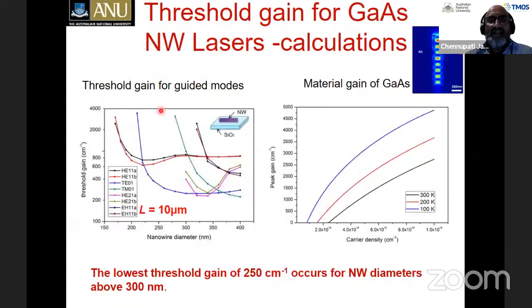So in fact, he has done calculations of the threshold gain needed for making these lasers work, as a function of the diameter of the nanowire. And you can see that the smaller the diameter of the nanowire, the threshold power, the gain needed to really make these lasers work, is very, very high. That means before you even start being able to make these lasers work, material damage takes place, and then these nanowires never will be lasing. If the diameter is below 200 nanometers or so, you can see you need to go to very high threshold powers, gains you need to have.